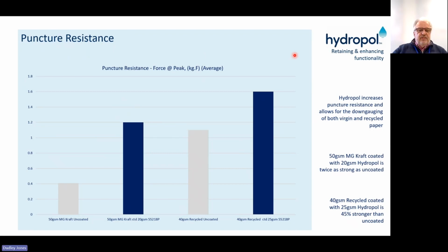If we think about puncture resistance, again, we've got a 50 GSM kraft uncoated, a 40 GSM recycled uncoated, and then we have them coated with a 20 GSM and 25 GSM of Hydropol. And you can see the puncture resistance is dramatically improved.